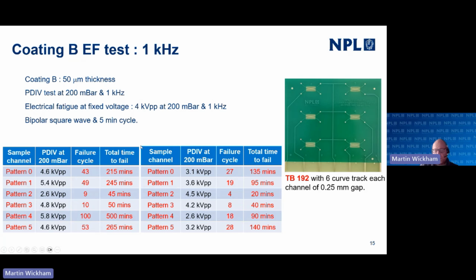We're going to start shortly. We don't measure the inception voltage as we go through the test at the moment, but we're going to start doing that soon to see how this inception voltage changes with pressure. But you can see here that we end up with a series of cycle failures, a total time to failure for each of these patterns.